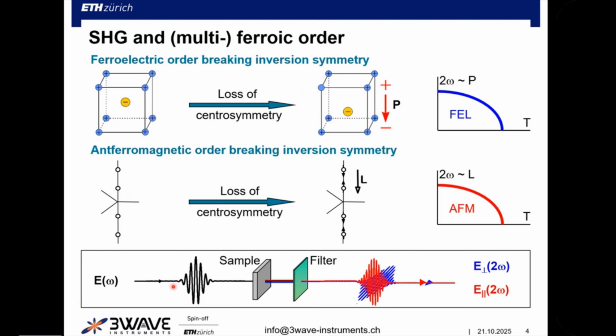So here we see that we send in light at omega. On the sample, it gets frequency doubled. You dump your omega light, and then you analyze the frequency doubled light. And because electric and magnetic order break symmetries differently, you see differently polarized frequency doubled contributions. One tells you about the electric order, one tells you about the magnetic order. So this is very neat, and it's all background free. This is the real big advantage.